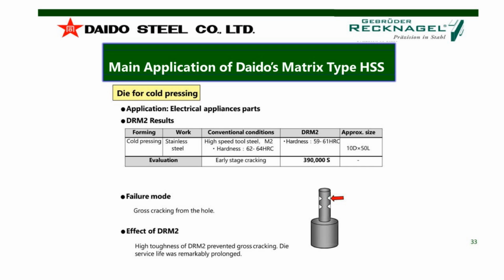The next application is a cold pressing tool, and as you can imagine, there's a big problem with the hole. The failure mode in this case was, of course, a massive crack, a massive break from the hole. The customer was using a standard high-speed steel, M2 grade, with a hardness of 62 to 64 HRC, and he had a very early cracking. With DRM2, he brought the hardness down to 59 to 61 HRC, and the tool lifetime goes up to 390,000 cycles, and that's really outstanding. That shows the extraordinary toughness of the DRM2 grade. The next, please.